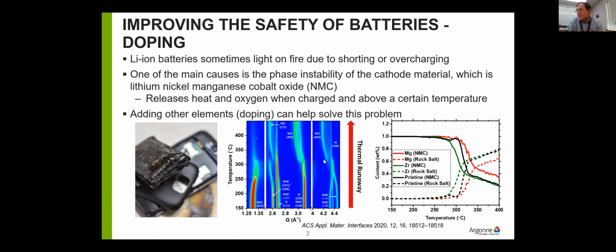And as you can see here from some data we took at the APS, we basically watched the structure and how it changes through time. Right around this 250 to 300 degree range, you start to see the structure change over to this nickel oxide phase. And that's when the battery goes into runaway. This also explains why you want to keep your batteries at as low a state of charge as possible, because you want to keep this cathode material as stable as possible, because this is really what's going to cause the worst kinds of fires and the final thermal runaway.